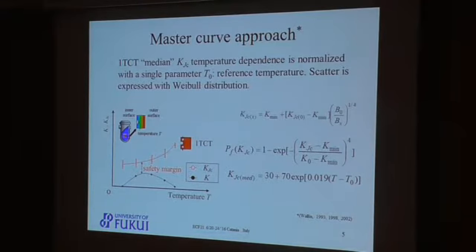Despite the efforts to apply the method, the approach is not without its limitations. For example, some results have presented that the master curve reference temperature obtained from SEB specimens and CT specimens show approximately 10 centigrade difference.